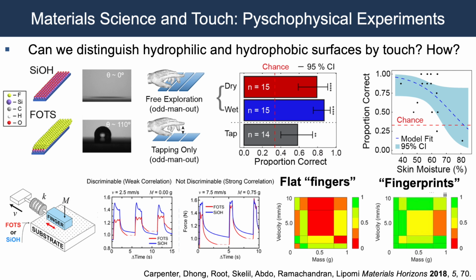Now, human subjects have fingerprints, and these flat fingers didn't initially have fingerprints, but when you put the fingerprints in, most of this discriminability matrix actually turns green, which means that the presence of fingerprints makes surfaces that differ only by surface energy feel more different based on sliding friction. And this is the well-known stick-slip phenomenon that occurs anytime you open a creaking door or in the action of a violin bow on a string. That's also stick-slip friction. The next thing we looked at was perception of softness.